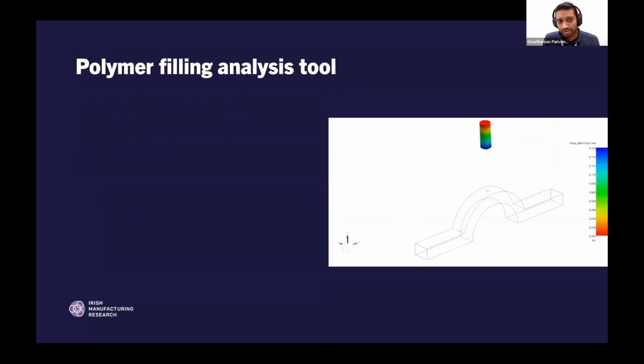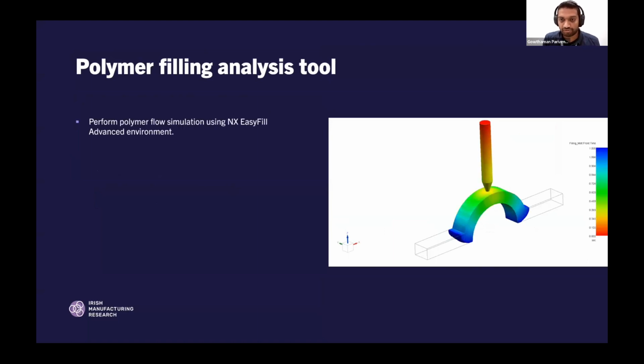We also run polymer filling analysis using the NX EasyFill Advanced environment. The reason we do this is because it offers us a quick view of where the hot and cold zones are, where the potential problematic areas are, etc. Based on this, we can design our cooling channels. We can either move the cooling channels closer to the hot zones or move them away from cold areas in order to achieve a uniform temperature gradient.